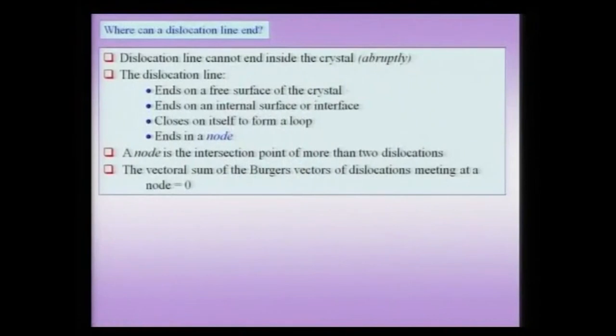Now, we ask ourselves another question. We have told in the previous lectures that a dislocation line cannot end within the crystal. So, where can a dislocation line end? A dislocation line can end either on the free surface of a crystal, or it can end on an internal surface or an interface, and such internal interfaces could be, for instance, a grain boundary. It can close on itself to form a loop, and we will of course take up some of these loops also. And finally, it can end